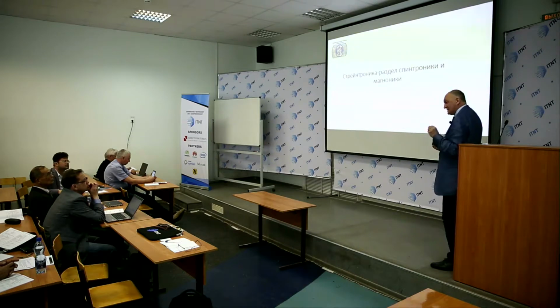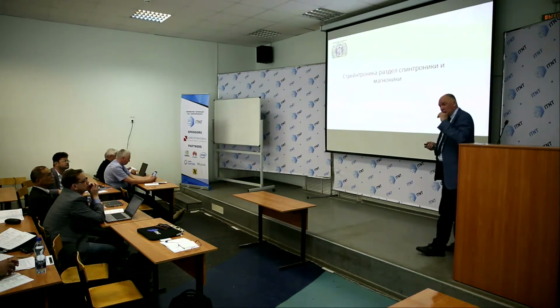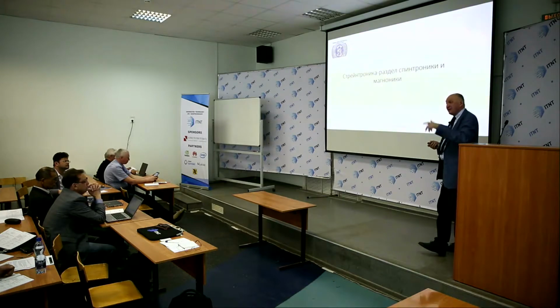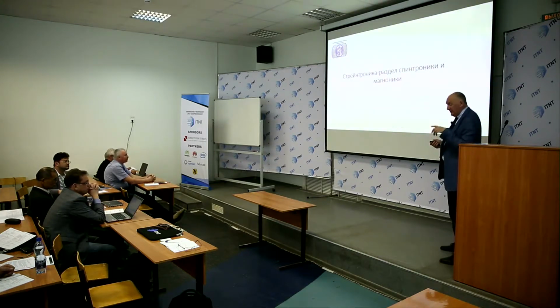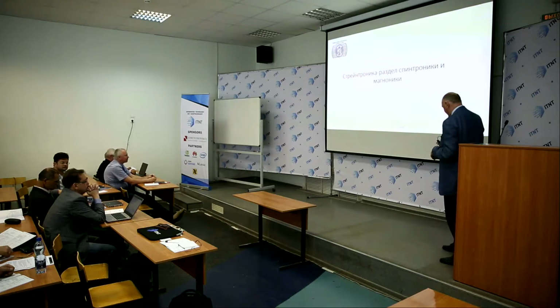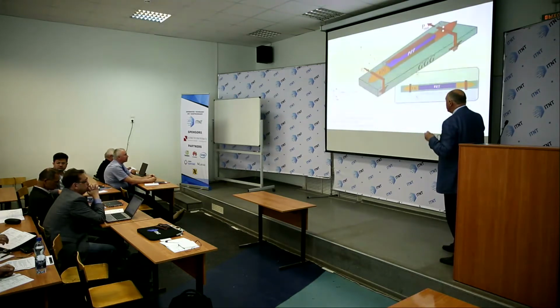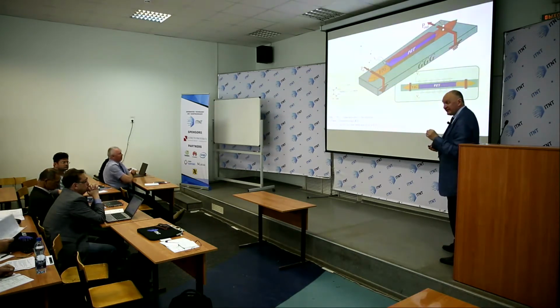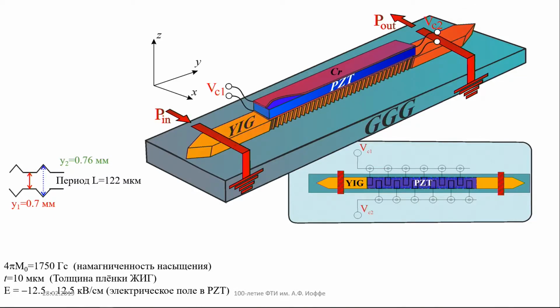Straintronics combines the possibility to govern magnetic materials by electric current, even in dielectric materials. This is due to the introduction of ferroelectrics, which are piezoelectric materials that can be governed by an electric field. So we change the strain. Strain changes the magnetic properties of an attached, for example, ferromagnetic film, and therefore the properties of a propagating spin wave can be governed by an electric field even though this material is a pure dielectric.